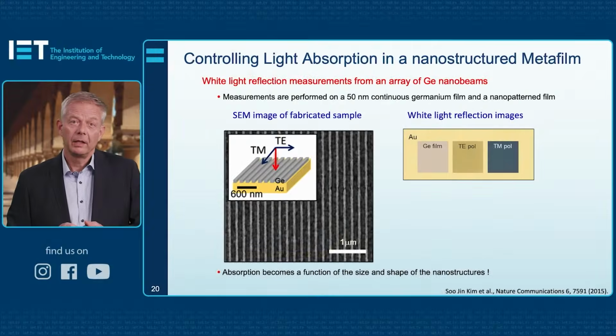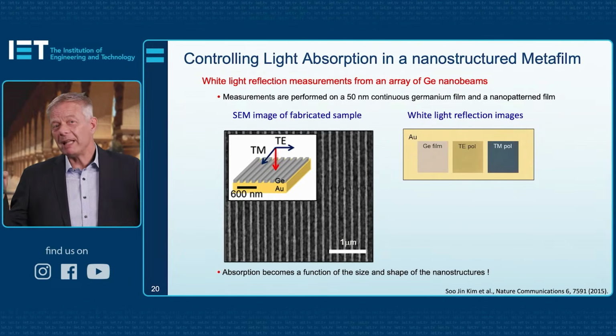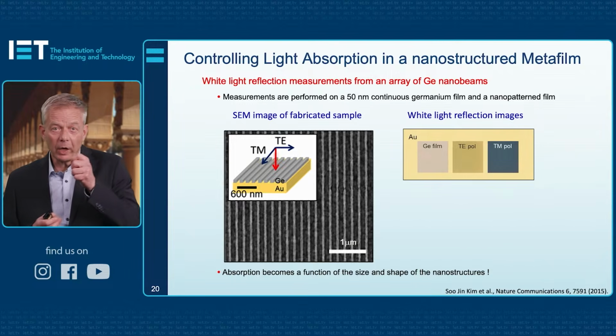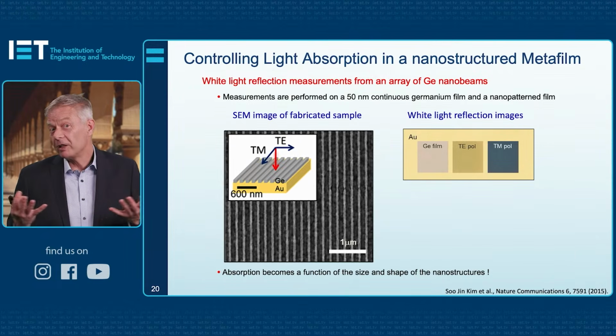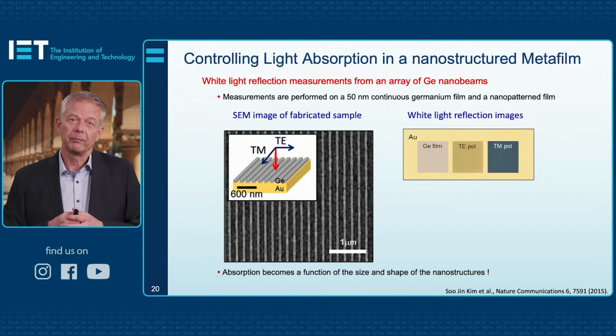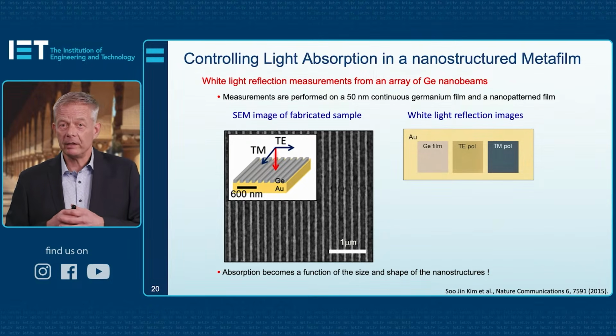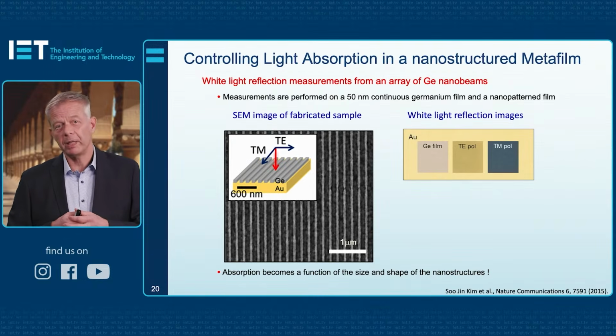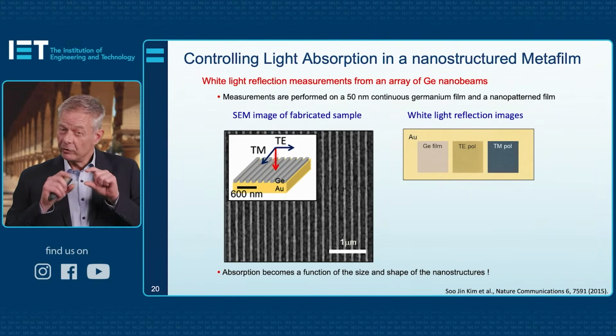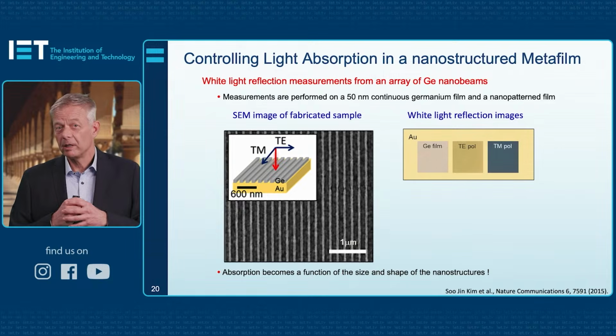If so, then it should be possible to make devices that operate at lower power, have new types of functions, could possibly operate at higher speeds, and provide entirely new opportunities and functions. Here's an interesting example where we made a metasurface out of germanium wires. All of these germanium wires can show resonances and change the optical property of the film. On the left side, you see a scanning electron microscopy image of a germanium film, just 50 nanometers in thickness, that we patterned by electron beam lithography.